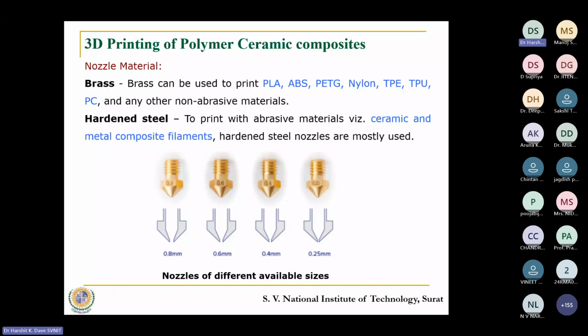Of course, when we go for the FDM process, we observe that ceramic particles will result in enormous wear of the internal nozzle. So we would prefer to go for hardened steel as a nozzle material when we want to print ceramic and metal particles with the composites. So in such cases, instead of brass, which is the most widely preferred nozzle material, we may go for hardened steel so that the life of the nozzle is extended, and the chances of clogging can also be reduced, if not avoided.